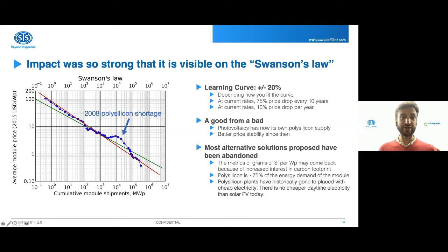So the metrics of grams of silicon per watt, or watt per grams of silicon, may actually come back because the polysilicon is responsible for 70% of the energy demand of one module. So in markets where the carbon footprint may be an argument, you may have some comeback of these kind of ideas, or at least moving the polysilicon plants to some carbon-free, carbon-neutral, low-carbon energy sources. So that's one trend I wanted to talk to you about.